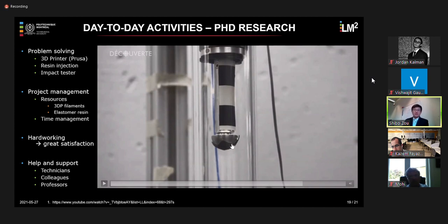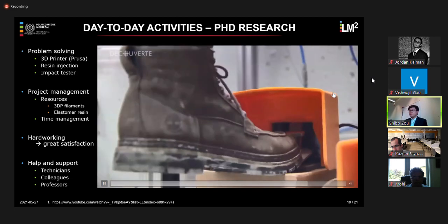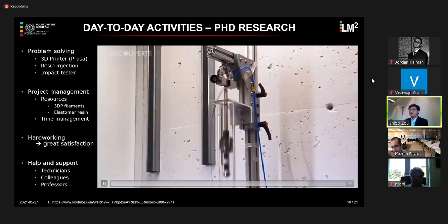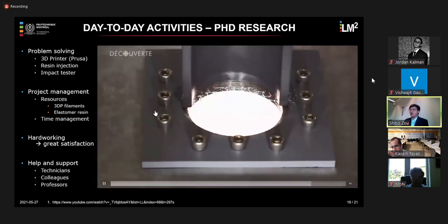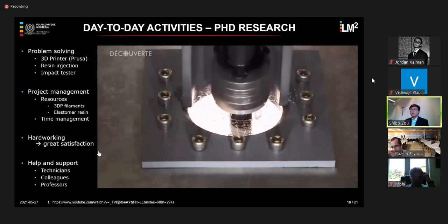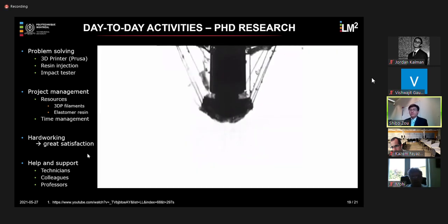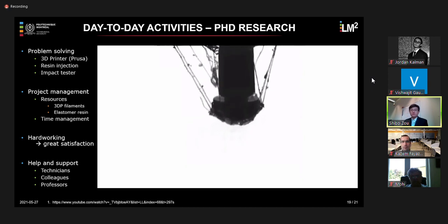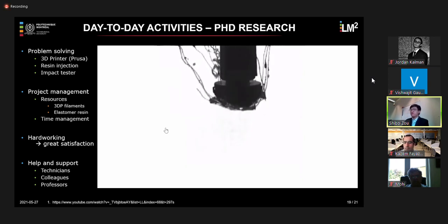Whenever the dart is at rest, there will be no force. And whenever the dart hits the specimen, we can detect the force with a very high data acquisition frequency, up to 7,000 data points per second. This way, we were able to measure the impact absorbing capabilities of our materials. Of course, the work was done with the collaboration between technicians and my colleagues, and also the supervision of my professors.